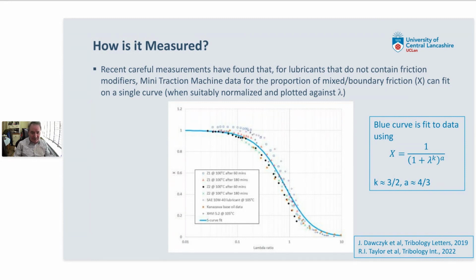And in fact, in some work I did with co-workers at the University of Central Lancashire, we compared this fit to commonly used mixed and boundary friction models, things such as the Greenwood Tripp model. We found that the Greenwood and Tripp model under-predicted the mixed and boundary friction proportion compared to the experimental data from Imperial College and this curve fit.